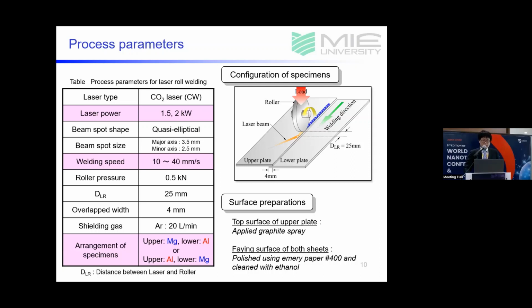As mentioned in the previous slide, we tried two types of arrangement of specimens. As surface preparations, we applied graphite spray to the top surface of the upper plate, and polished and cleaned the faying surface of both sheets.